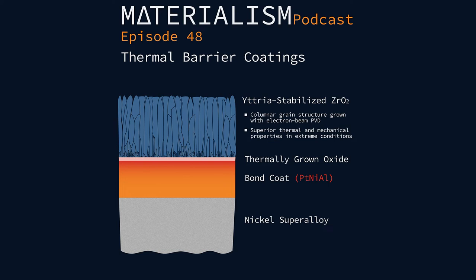Now, if you compare that to plasma spraying also, remember that they both have to have lateral strain compliance, and really the only tool that you have in plasma spray coating to provide that lateral strain compliance is incorporation of porosity. If you've taken a ceramics class, you probably learned that the more porous a ceramic is, the more compliant it tends to be. You reduce the Young's modulus, and so that's about what you have. Now, that's beneficial because it's going to reduce the thermal conductivity, but we know this also degrades strength. Both of these microstructures that get generated have porosity, and that's going to reduce their strength.